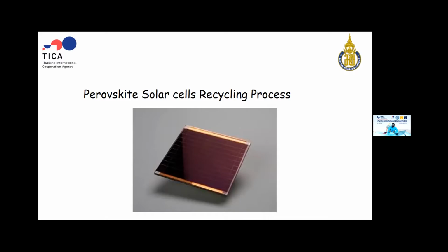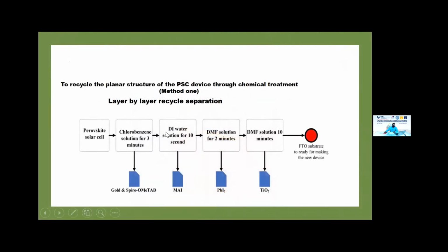So my work was to fabricate a new solar cell and ensure a unique method for recycling. So this is the layer by layer separation process. First, we fabricate the planar structure perovskite solar cell, and then we recycle, using a four-step method like layer by layer separation. First, chlorobenzene solution used for 3 minutes, and remove the gold layer, because as an electrode we use gold, and spiro-OMeTAD for the HTM layer. So we remove it by using the chlorobenzene solution, and after that use DI water to remove the methyl ammonium iodide, and after that